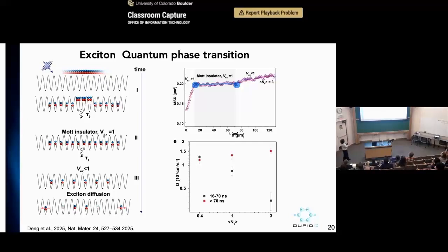And then at some point, once they do that, some of the sites in the center will more likely be left with 2 excitons in one site. And so the initial very fast expansion is coming from this part. And then, as I showed you, the 2 excitons have very rapid annihilation loss. So after the annihilation concludes, you're going to enter this Mott regime. That's where you see the motion of excitons is totally suppressed, right? So this is when you're in the Mott state.